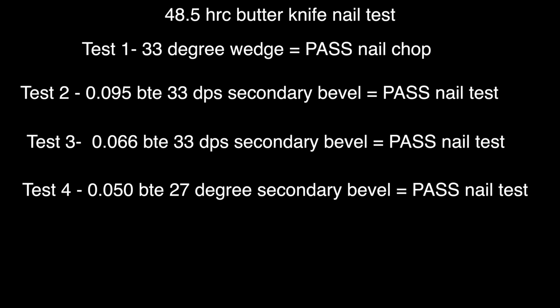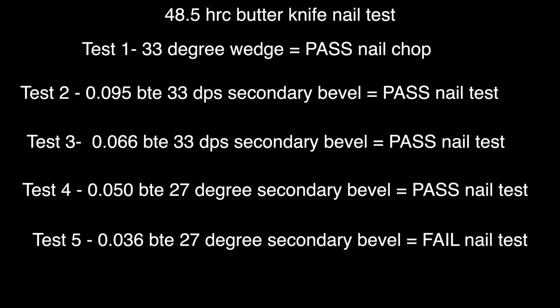Test 4, at 50 thousandths behind the edge. We're getting into the realm of off-the-shelf stock survival knives here with 27 degree secondary bevel equals pass the nail test. Insane. Test 5, at 36 thousandths behind the edge and a 27 degree secondary bevel is our failing point. So somewhere between 50 thousandths and 36 thousandths behind the edge is our failing point.